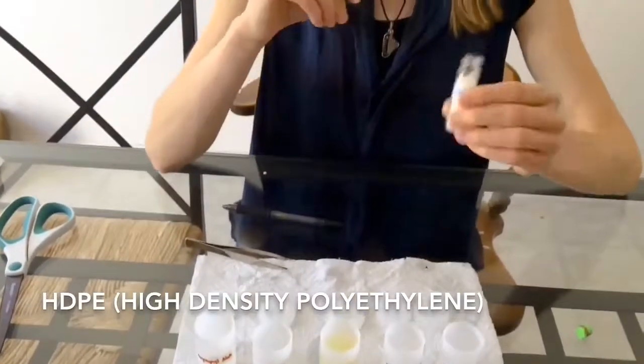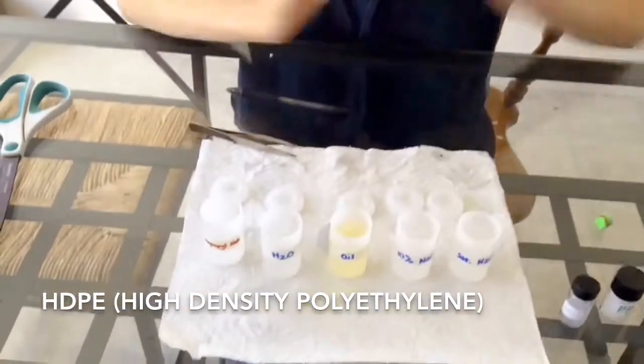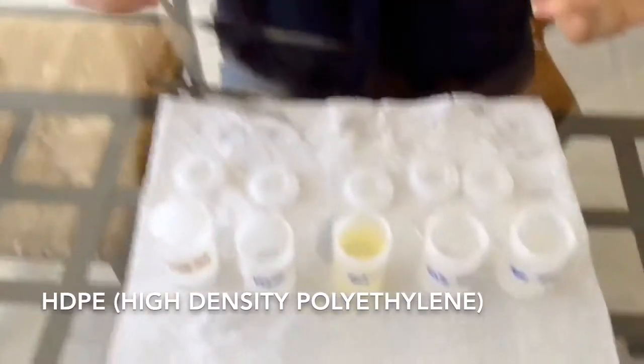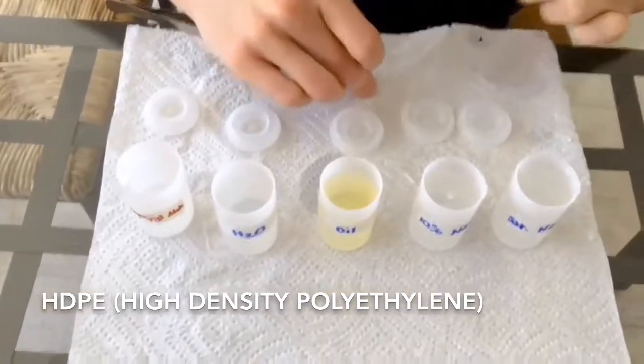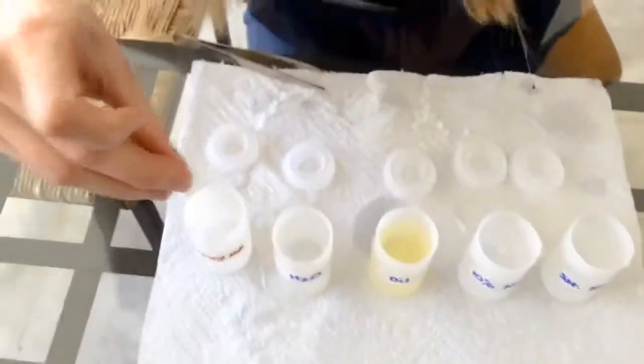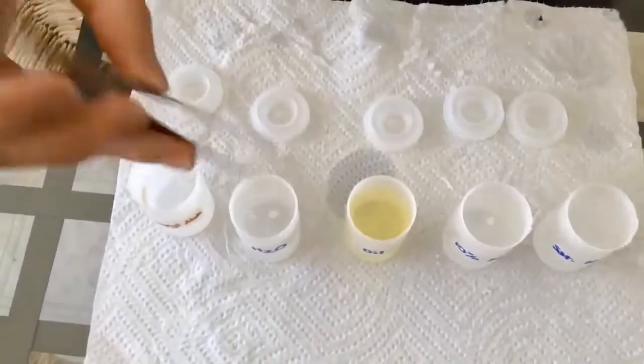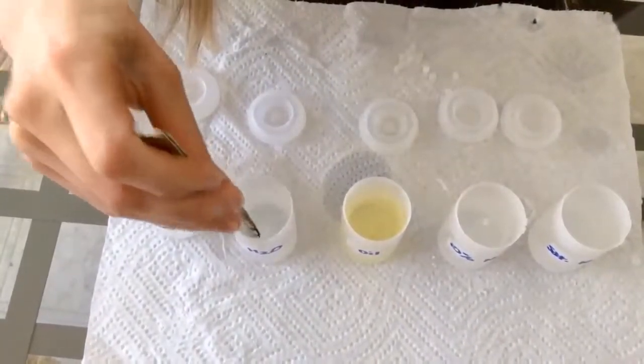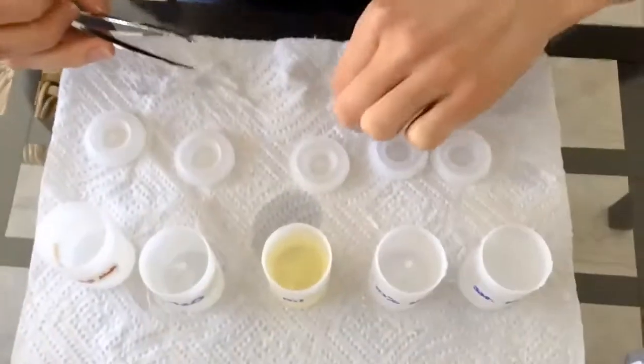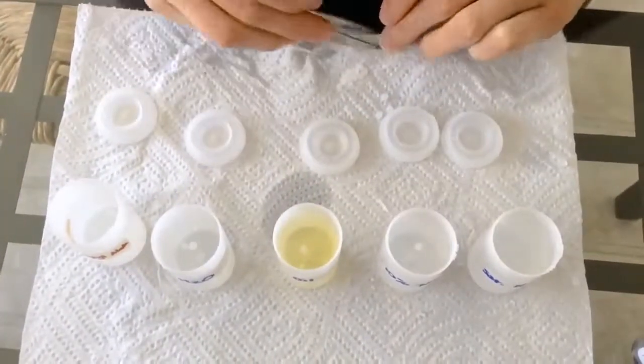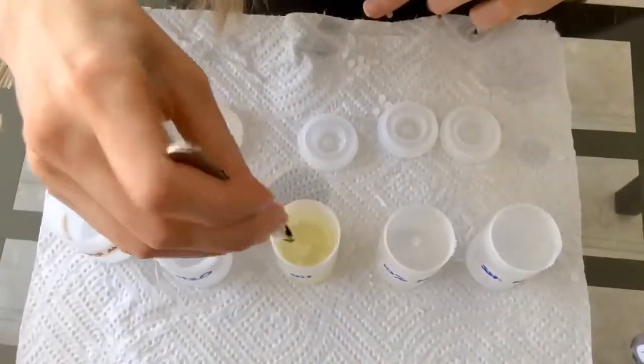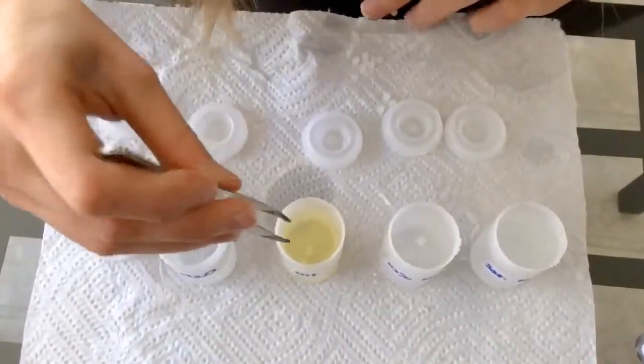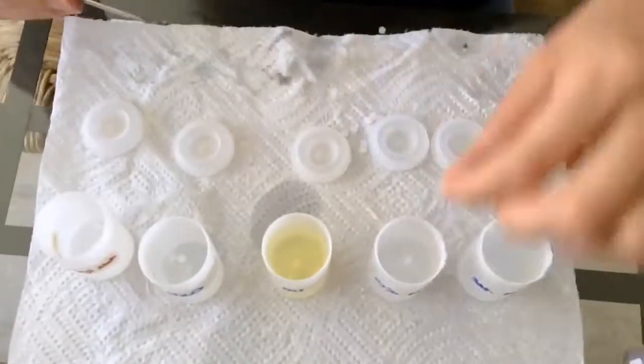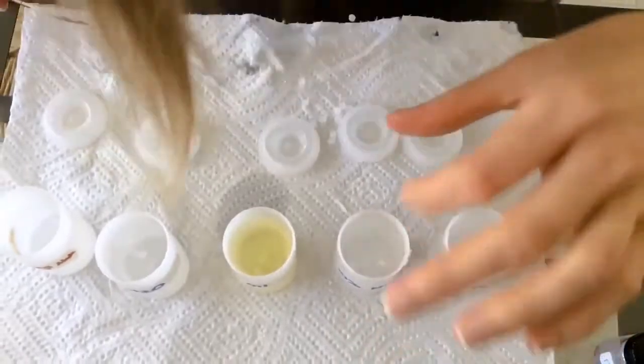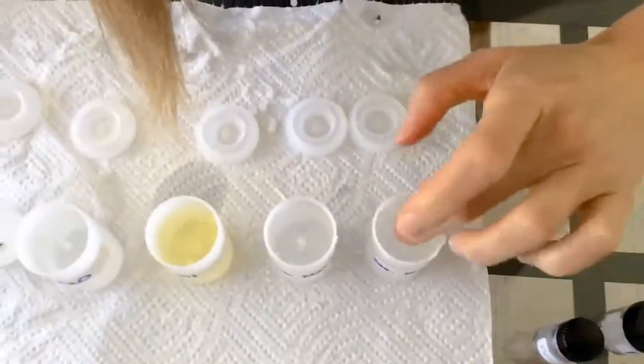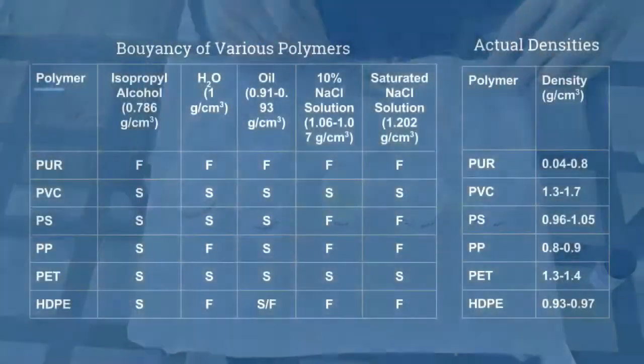The last polymer I'm testing is high-density polyethylene. It's used in piping as well as plastic containers. We'll test it first in isopropyl alcohol, and it sinks. But in water, it's floating. In oil, it's kind of between floating and sinking. It's hovering there in the middle. It is floating on 10% NaCl, and it floats on saturated NaCl.